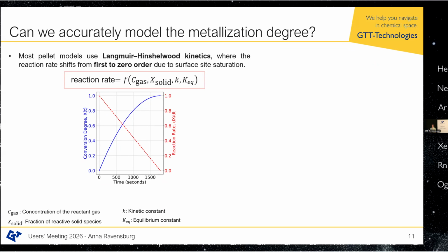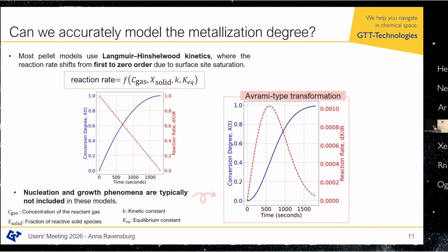The problem is that we are all probably metallurgists, or most of us, and what we learned in university about how this works is that first grains have to nucleate and then they have to grow. But this approach does not consider any of these nucleation and growth phenomena. And this is a big problem, because if you would look at the same curves with nucleation and growth, then it would look somehow like this. So you would have some kind of incubation time, because you first need to form the nuclei, and then they can grow. That's also why the blue curve has this dip in the beginning. And that also means that the reaction rate is not linearly decreasing. It is first increasing a lot, because you form nuclei.